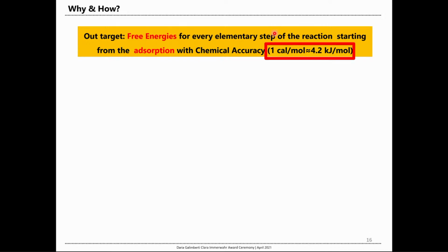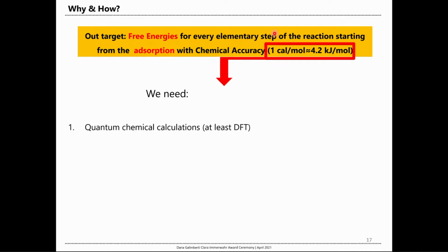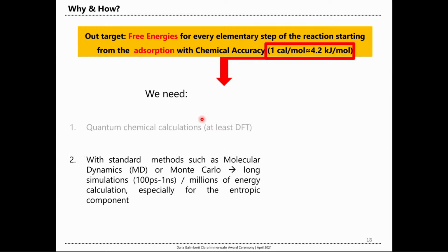And to reach this target, we know that this kind of accuracy can be reached in general only if we use quantum chemistry calculation, at least DFT. And the problem is that we also know that the standard method to compute free energies is to use molecular dynamic simulation or Monte Carlo simulation. But these simulations require either long simulations for molecular dynamics, from 100 picoseconds to 1 nanosecond, or millions of energy calculations in the case of Monte Carlo simulation. And this is due to the fact that the entropic term is not taking contribution only from the positions near the minimum of the potential energy surface, but it's really feeling also all the other points of the potential energy surface. You really need to have a good description also of these points far from the minimum.